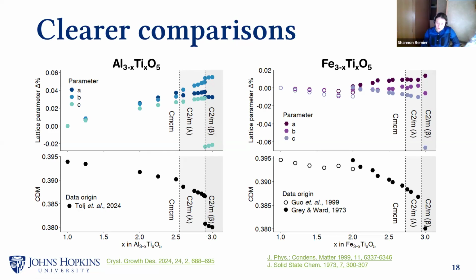Sometimes phase transitions are very subtle. For example, if you have something that was orthorhombic and the 90 degrees changes to 90.1 degrees, it can no longer be defined as orthorhombic. And so we would call that a continuous phase transition because there hasn't been an abrupt jump. But occasionally the atoms will reach a different configuration such that the lowest energy configuration is now very, very different from the starting one. And that's basically what's happening here. So a roughly orthorhombic structure for a long time was preferred by these atoms, but once there is sufficient titanium added into this structure, there's now a lower energy configuration where the lattice parameters are significantly different from their starting point. And that's why we have this jump here in the CDM.